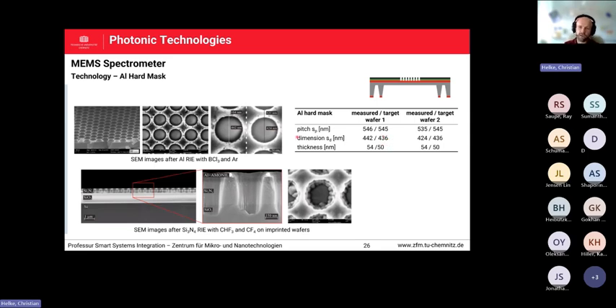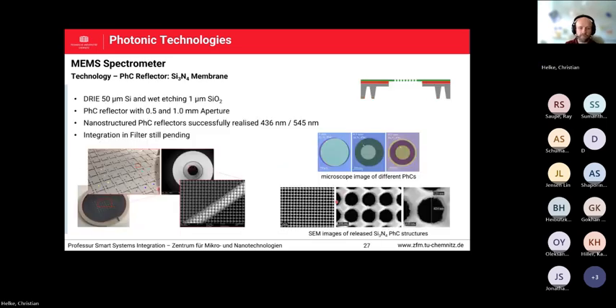And after the opening of the hard mask, we etched the silicon nitride layer, which you can see, for example, here. And again, we etch down to the silicon dioxide layer, which then at the end will be etched from the backside away, so that you have really the freestanding silicon nitride membrane layers with holes in it. All of these things which look here not really nice are some polymers. After the etching itself afterwards, the holes look really, really nice, much better.